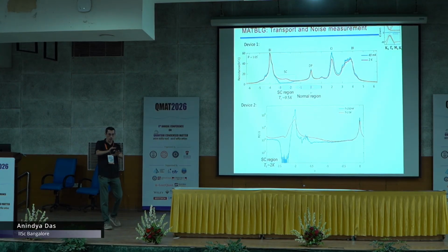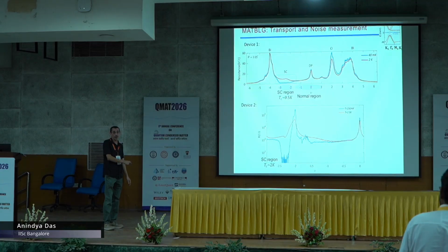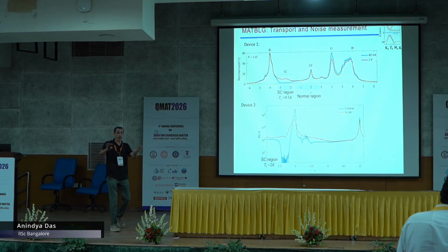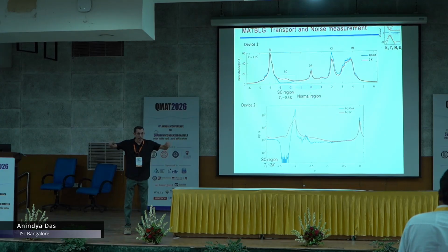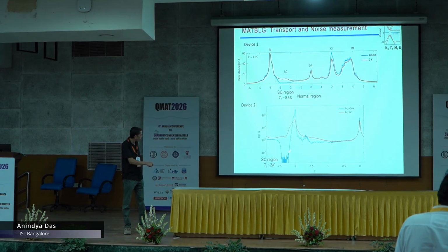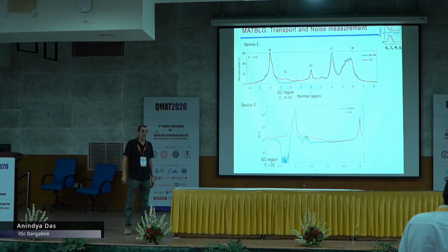That is known, because if you have angle inhomogeneity, with metal and insulator regions and a percolating channel, then you will not see the insulator, but superconductivity is easy to see because it's a parallel path. But in this second device we see a clean correlated insulator. These are the signatures of disorder. By the way, these are not disorder from atoms or defects, mostly angle inhomogeneity, but we believe this is one of the cleanest devices we have.